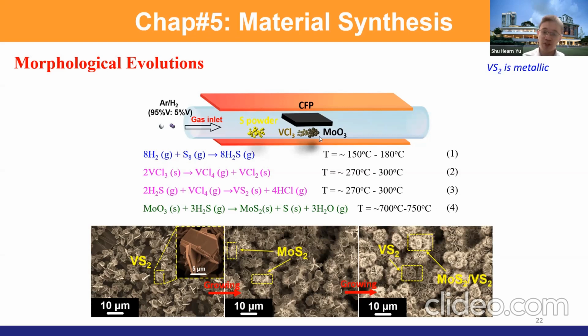So if I put the precursors here, what will react first is the vanadium chloride with the sulfur. Then it will form vanadium disulfide. So these are vanadium disulfide. I ramp up my CVD process very slowly. After that, I ramp up to about 800 degrees. You can see that at around 750 degrees, the molybdenum oxide starts to decompose and evaporate. So you can see there's MoS2 growing on the vanadium disulfide.